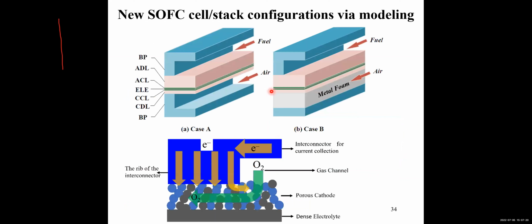In the past few years, we have looked at how to optimize the rib size and improve stack performance. The rib size is very important: when it's too small, current collection becomes challenging and difficult, but gas diffusion under the rib is easier. However, if the rib size is large, current collection is easier, but gas diffusion, especially oxygen diffusion under the rib, becomes an issue.